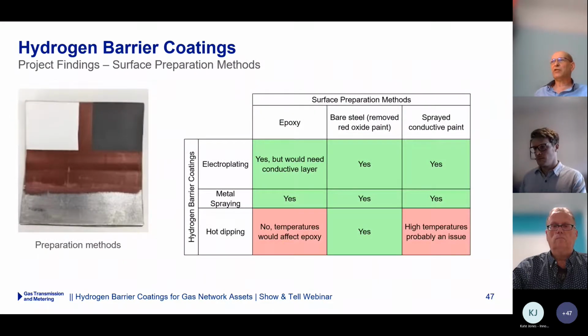Part of that consideration was to think about the preparation methods that will be needed to convert the existing network and the existing condition into something that we could apply a coating to. We made a visit to the National Grid Ambergate site, and that was very informative in trying to understand the real condition of the pipeline components when they're in service. National Grid provided us with some samples, and we ran some trials on some of the preparation techniques, things like scratch brushing, grit blasting, chemical pickling, and so on. These studies showed that there's a range of preparation processes that could be applicable for different barrier coating methods and allow some flexibility in the approach that we could use for different asset types. Next slide, please.